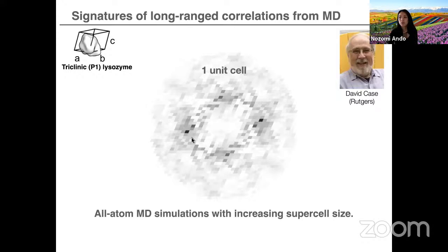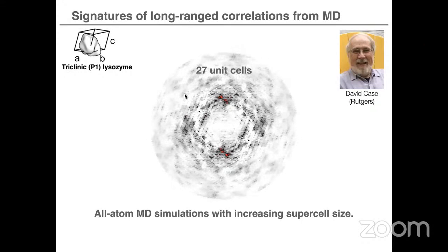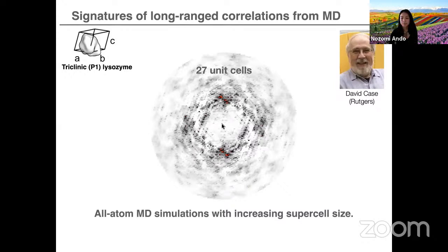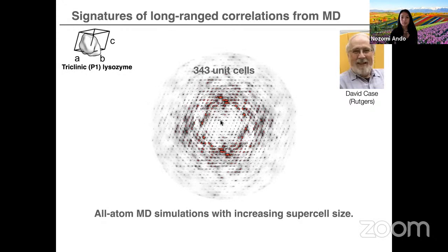But if you increase the simulation size, so the box size, turn it into a supercell, then you start seeing a change in the diffuse scattering pattern. And Dave went on to simulate a really large supercell, 343 unit cells, again, still with the periodic boundary conditions. And now you start seeing clearly the halos emerging, right? There are no Bragg peaks in this calculation, yet it appears like there are because of those halos. So this was another piece of evidence that told us that if you allow your simulation to be large enough such that different unit cells could be talking to each other, then you will start seeing those signatures in the diffuse scattering.